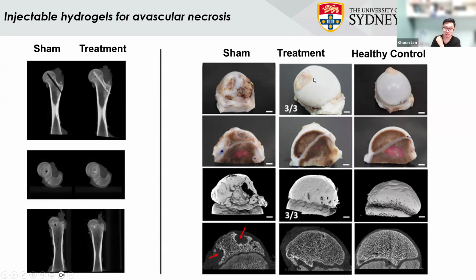And in the ones where we drill a hole and then inject the hydrogel with the growth factor, in this case, you can see in the treated samples, you also get really nice preservation of the cartilage and also preservation of the overall femoral head shape.